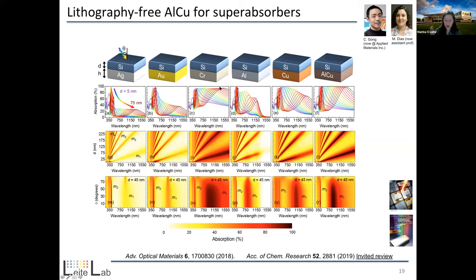However, if you spend a lot of time in the lab and making samples, you might know that making high quality chromium is far from trivial. It's a material that actually has a lot of issues when we do a sputtering deposition. Now we decided to then look again into earth abundant options such as aluminum and copper. And then she saw that copper looked much better. And once we combined the two, we could actually achieve 99% absorption.